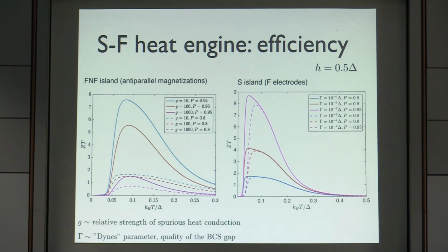The more interesting thing is the power conversion, because this is something that you cannot get without this ferromagnetism. What I have done here is to calculate this figure of merit in the presence of the spurious effects. The spurious effects mean that you have extra heat conduction channels, except for the electronic one. Typically they are related with the actual phonon conduction. Here I'm assuming that it's the electron-phonon coupling that is the extra heat conduction channel.